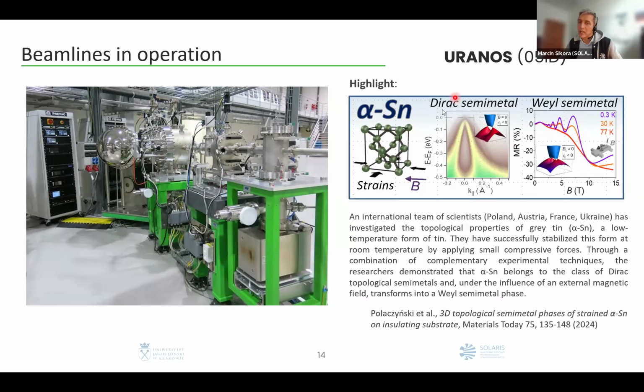And in this highlight, it was shown that depending on the stress given to the sample and the change of temperature, it was possible to observe a topological transition in alpha tin, from this Dirac semi-metal with two nodal points to a Weyl semi-metal with four nodal points. So this beamline has a very high resolution, especially in energy, but also in terms of momentum. And I think it has recently also installed a spin filter. So it's also possible to do spin-resolved studies, which are excited with photons of different polarization, not only linear,